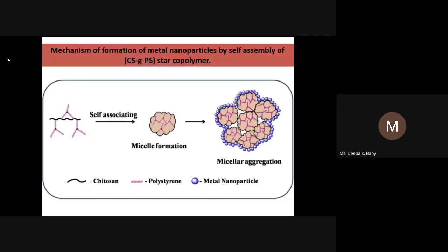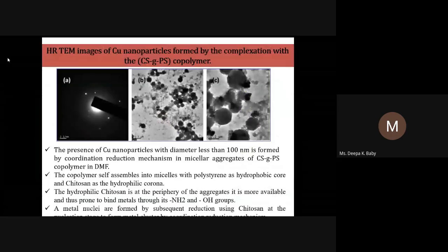These are the TEM images of the nanoparticles. You can see nanoparticles embedded in the micelle, and the nanoparticle size is 20 nanometers. And this is mainly due to a mechanism, that is the coordination reduction mechanism. I'm not discussing this coordination reduction mechanism. And this is the proof for the metal nanoparticles.